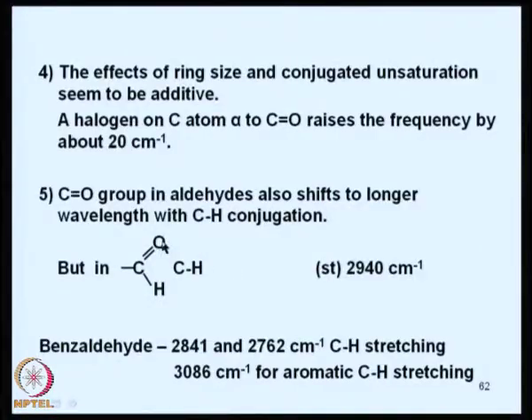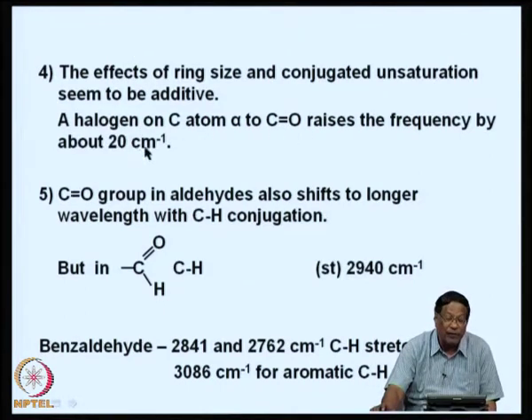calculating precisely the wavelength at which the peak should appear, lambda max. Now, it is not possible to do it here, but similar effects are seen here. For example, this alpha halogen on a carbon atom shifts the peak by about 20 centimeters inverse. So, the carbonyl group in aldehydes also shifts to longer wavelength with conjugation itself like this, and this stretching frequency appears at 2940 centimeters inverse, whereas for benzaldehyde it appears at 2841 and 2762 centimeters inverse.